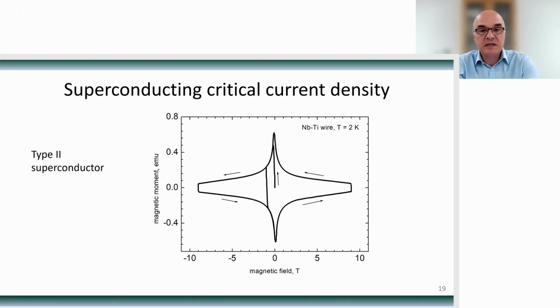We start with the case of simple geometry. So if your superconductor is a simple cylindrical rod, then you can derive a simple formula which relates the dimensions of the sample, the critical current density, and the width of the hysteresis loop, which I show here with this blue arrow. So the hysteresis loop here is what we record. If we start from 0, the center of symmetry of this graph, and the field here was taken down to negative, and then back up to maximum positive, and back to 0 to negative, and back to 0. So the superconductors always produce these nice looking characteristic diamond shape hysteresis loops. And the information about the critical current density is all contained in the width of the loop.